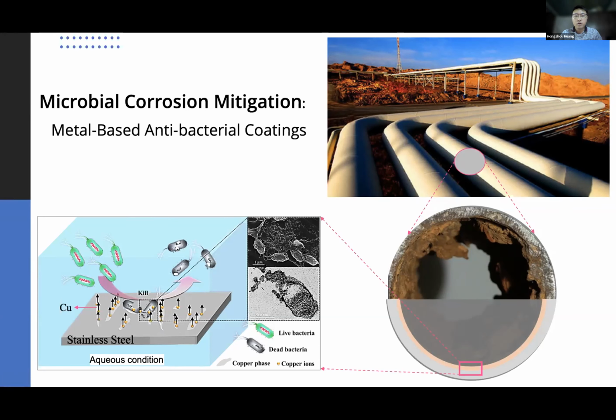We're going to make the antimicrobial coating inside the tube, as shown by the orange color in this figure. And the coating material we choose is the copper containing stainless steel. Copper here is added as the biocide to kill the microorganism, which will cause less impact to the environment than the conventional chemical biocides. And the stainless steel is known for its high corrosion resistance. So you can imagine the combination between copper and stainless steel could provide long-term protection to the tube in a more cost-effective and environmentally friendly way. Thank you.